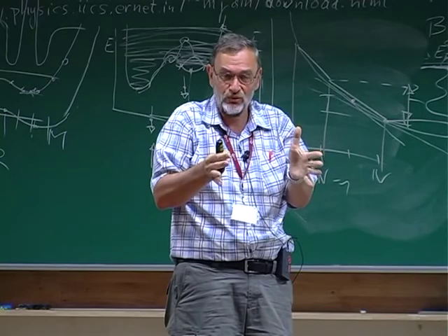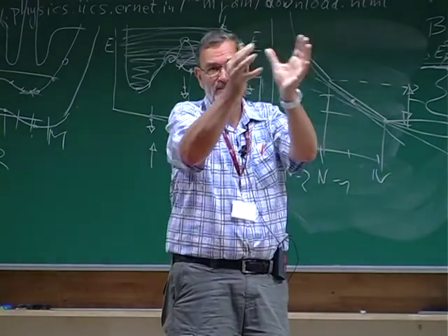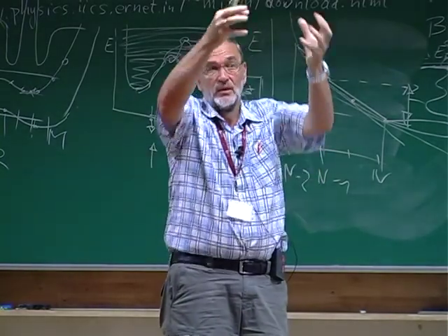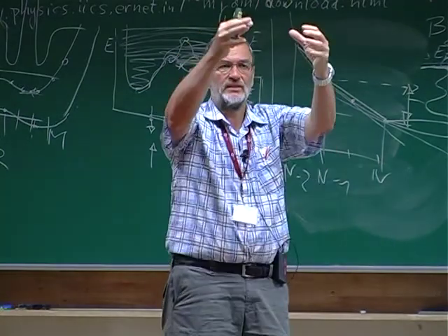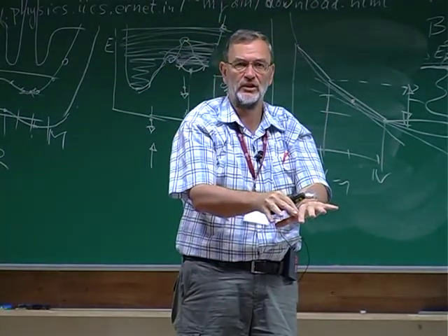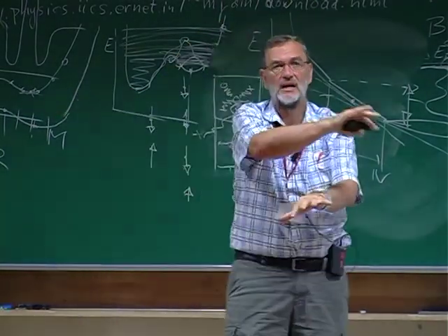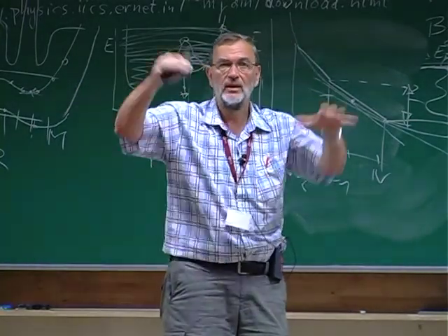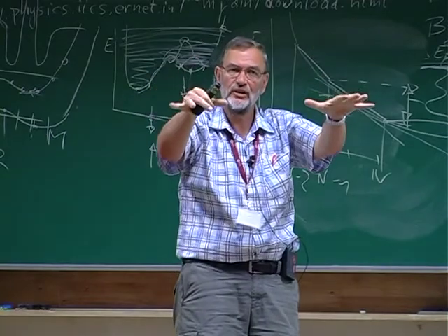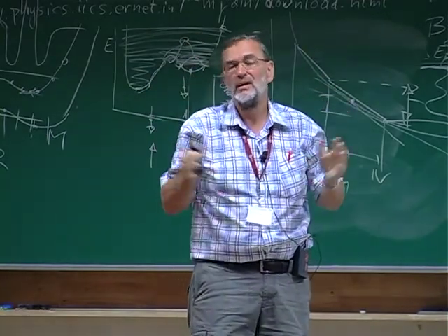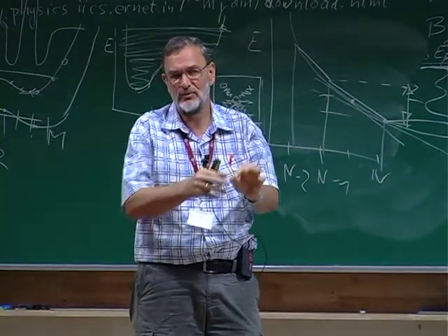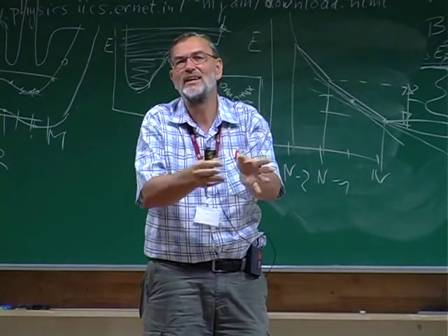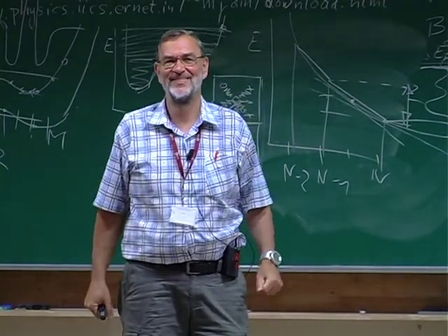If your supercell is too small, only this one atom where the hole is must react completely and gives you a too strong downward shift. If there are other atoms around which have no hole, they can contribute to the screening, and all the electrons can shift down a little bit more. And if your supercell is not big enough, you can mimic this by making a little bit smaller core hole. Okay?